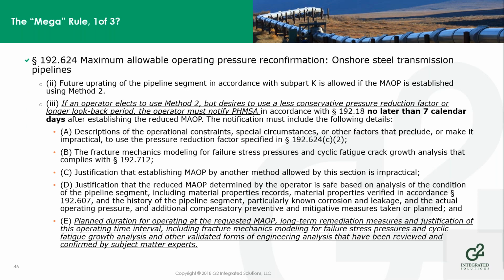As well, for method 2, an operator elects to use method 2 but desires to use a less conservative pressure reduction factor for a longer look back period, the operator has to notify PHMSA again. And there we are again with 192.18, no later than 7 calendar days after establishing the reduced MAOP, and the notification has to include this information.